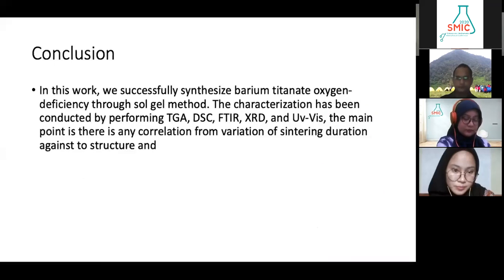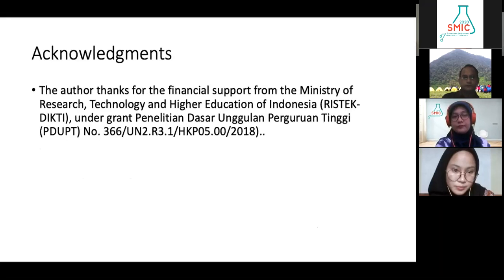Then for the conclusion, in this work, we successfully synthesized oxygen-deficient barium titanate through the Sol-Gel method. The characterization was conducted by performing TGA, DSC, FTIR, XRD, and UV-Vis. The main point is that there is a correlation between the variation of sintering duration and the structure. And we would like to thank the Ministry of Research, Technology and Higher Education of Indonesia.